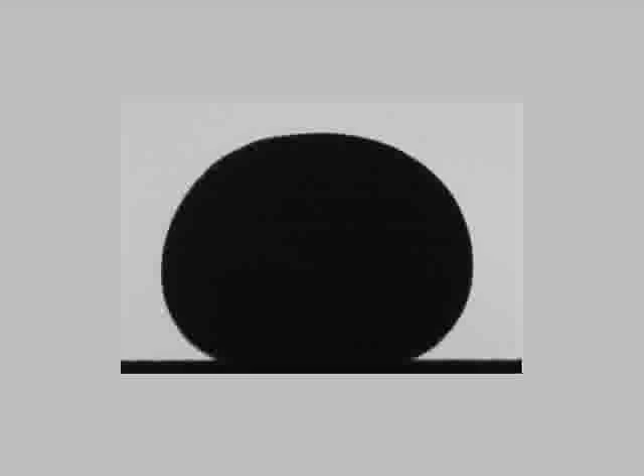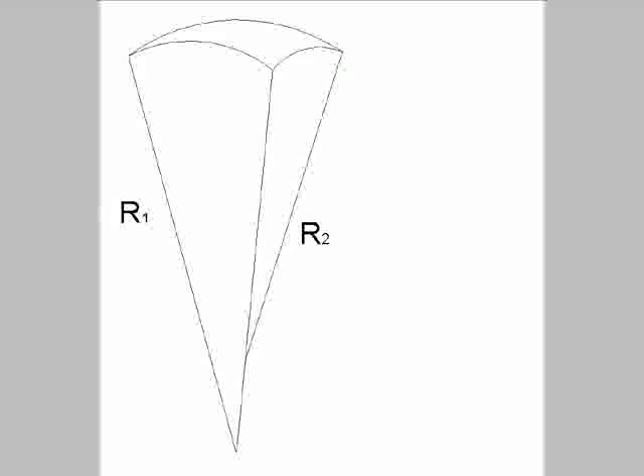This is a sessile drop of molten solder over an alumina plate at 200 degrees C. The measured value is 482 × 10⁻³ Newton per meter. The calculation of the surface tension is made possible thanks to the development of a new mathematical algorithm.